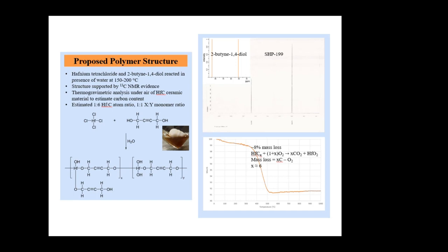We believe that the polymer was synthesized by the reaction of hafnium tetrachloride with 2-butyne-1,4-diol in the presence of water to create a dark brown polymer with the structure shown here. Carbon NMR supports the structure. Here we see an NMR spectrum for the plain polymer, which is the main spectrum, and the NMR spectrum of the butyne diol starting material in the corner. We see the same number of peaks in roughly the same position, one at 50 ppm and one at 83 ppm. Because the carbon is unchanged between the starting material and the final polymer, we would expect the carbon NMR spectra to resemble one another.